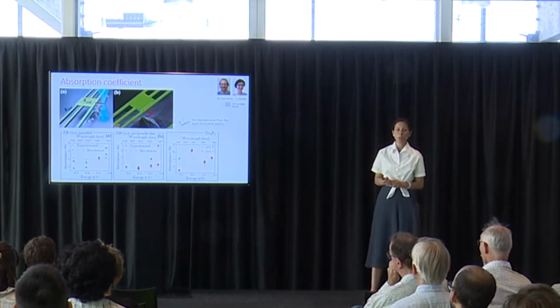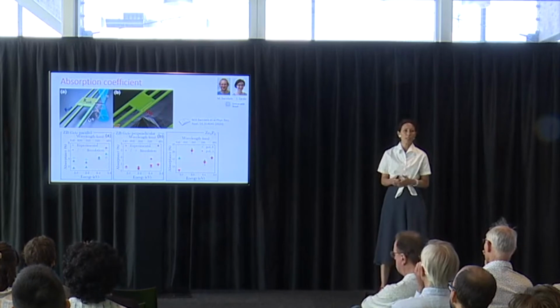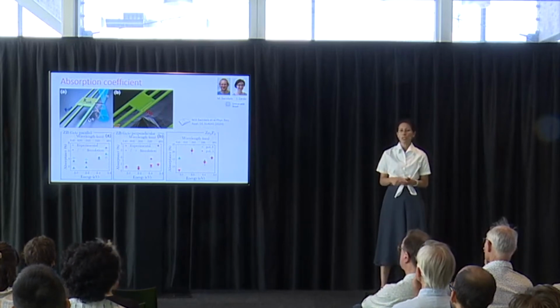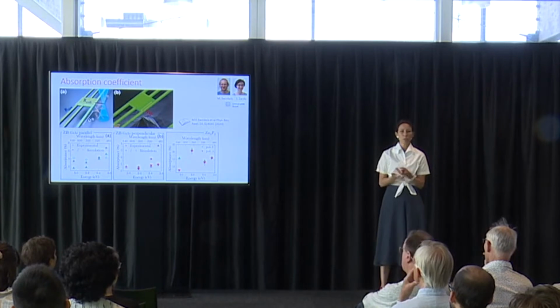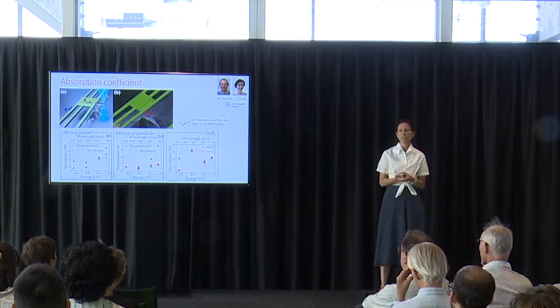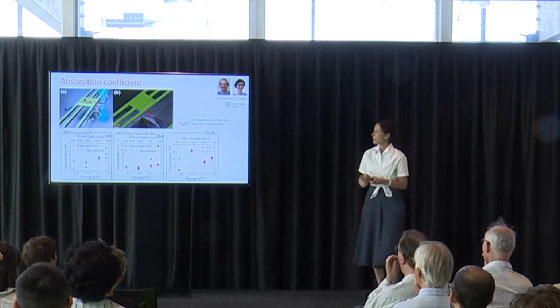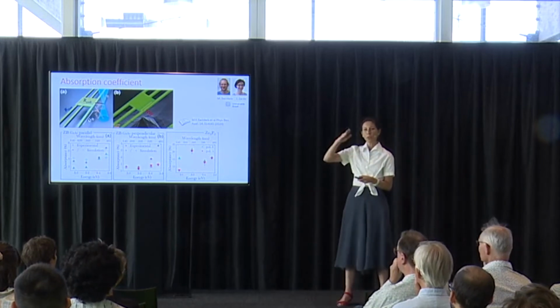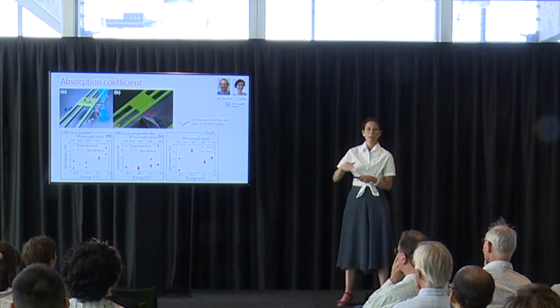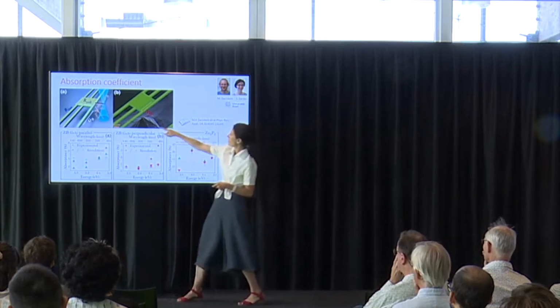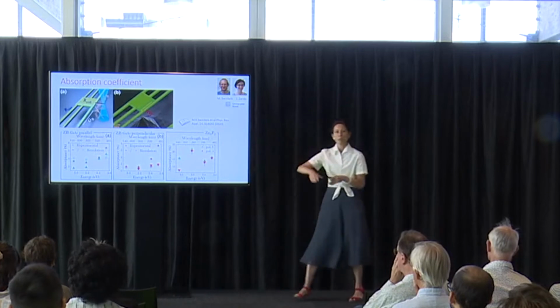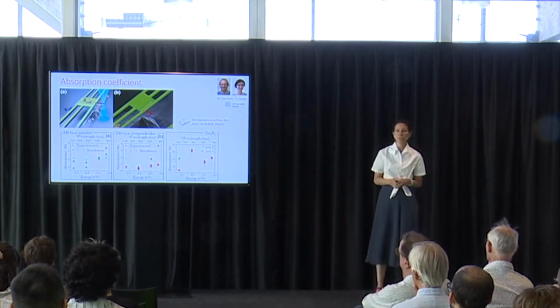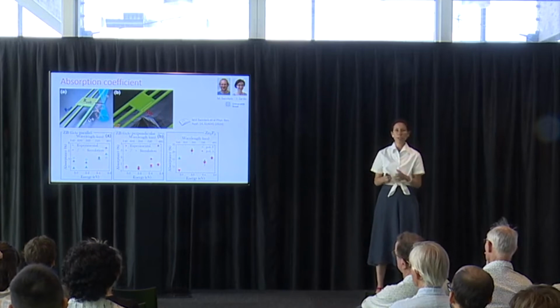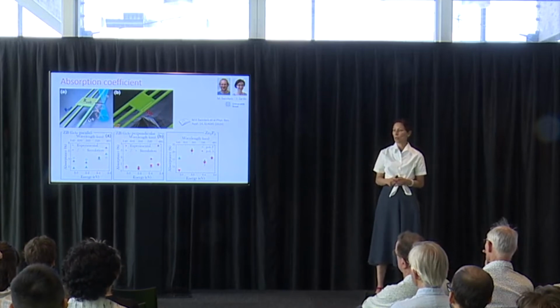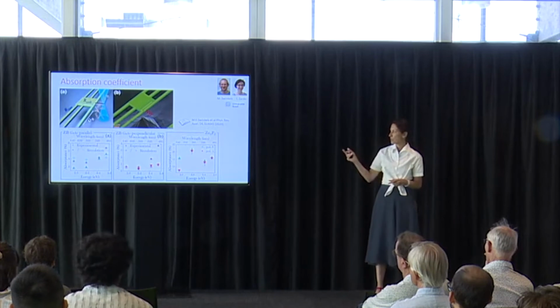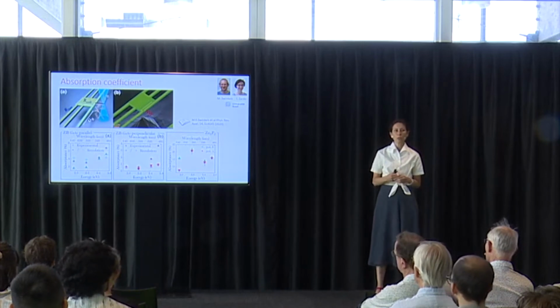Another way of looking at the absorption coefficient and comparing with different materials, and here also you need a nanowire configuration, is to measure absorption by measuring the change in temperature in the material when it's illuminated by different wavelengths. So in this experiment from Ehrler in Basel, she put the nanowires on top of a thermometer, and this is what you see here. This is a suspended microthermometer. You put it there, you illuminate, and you measure the change in temperature. Of course, you need to simulate a bit what happens related to the absorption coefficient, but we compared several materials. And this was, in fact, also a collaboration with the TU Eindhoven, where there are also other materials from them.